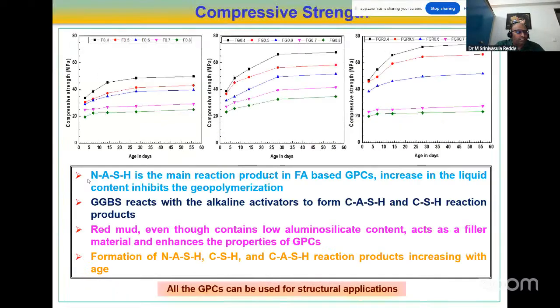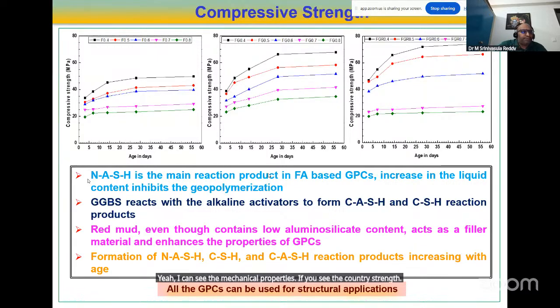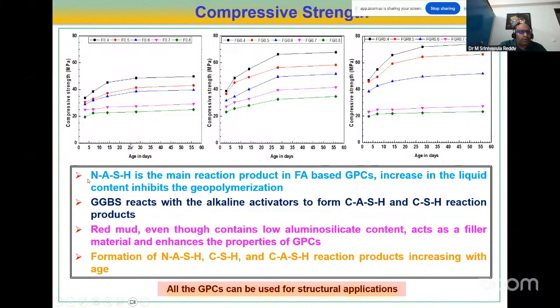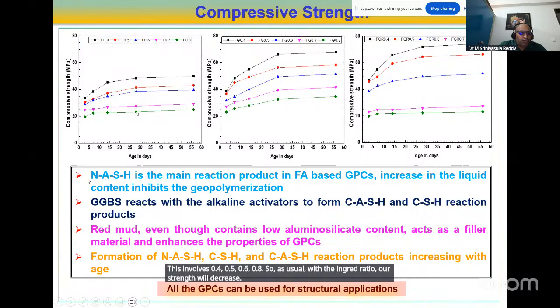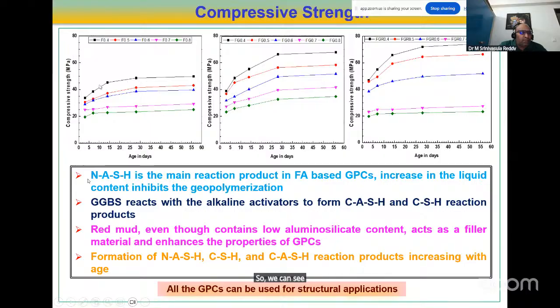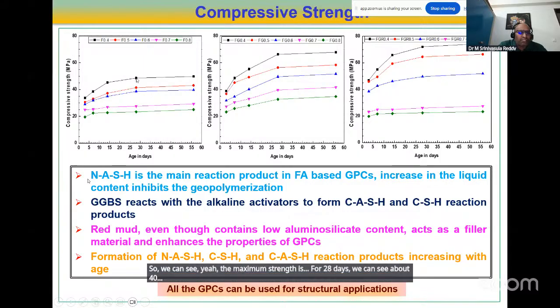Here we can see the mechanical properties. If you see the compressive strength, these symbols are 0.4, 0.5, 0.6, 0.7, 0.8. So as usual, with the increase in the ratio, our strength will decrease. We can see the maximum strength is at 28 days, about 47 to 48 with fly ash alone.